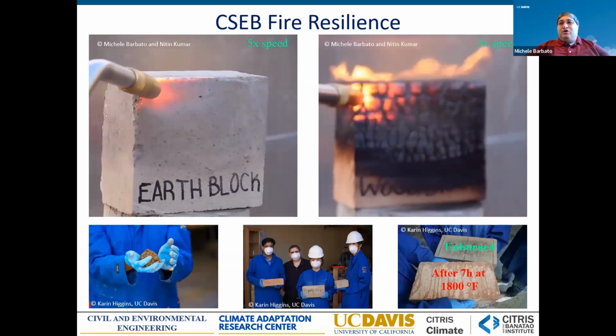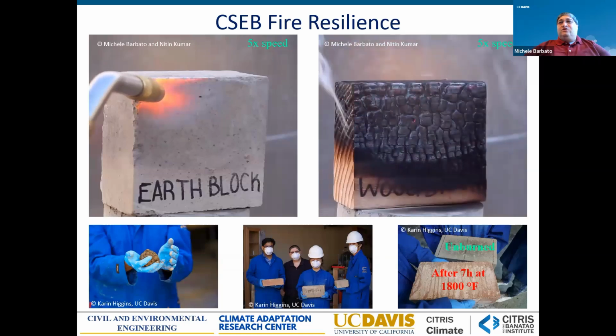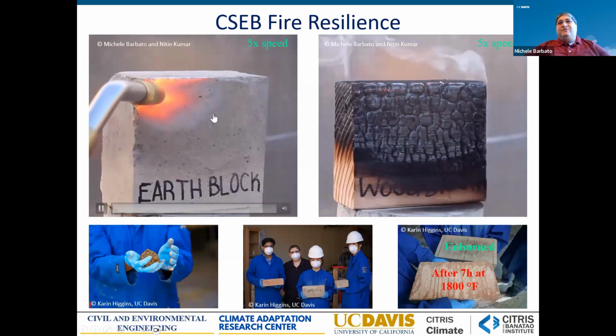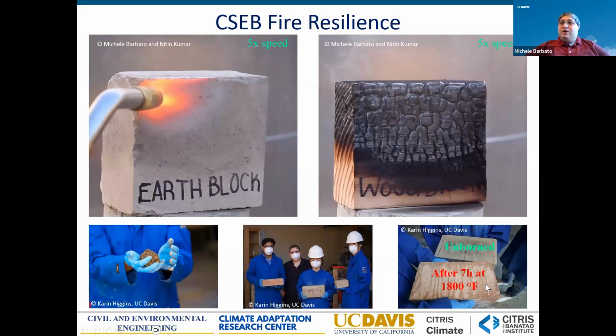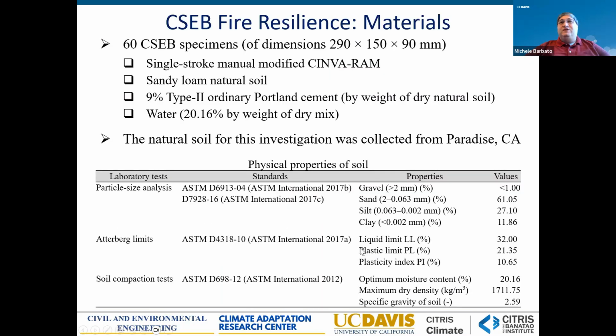and wood obviously burns. Not only that, but you can see that fundamentally, even under a propane torch at 3400 Fahrenheit, the only effect that you can see on our blocks is a change in color. And we tested our blocks in a furnace for a very long period of time at very high temperature. And so I'm going to show actually some of these results.